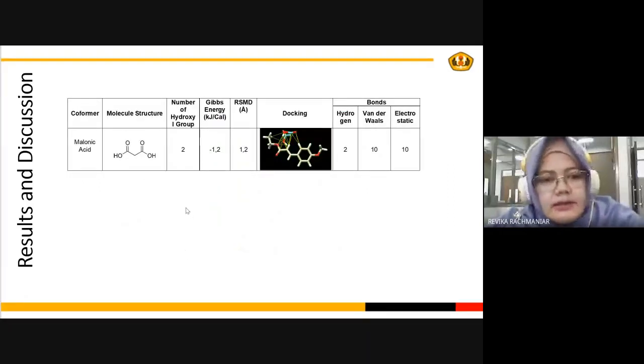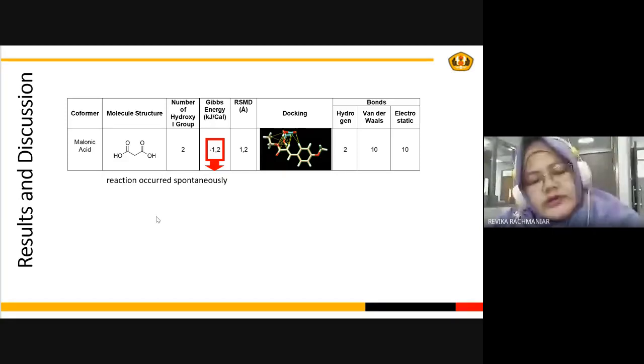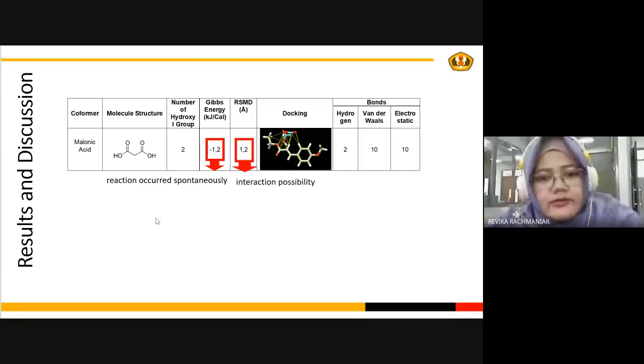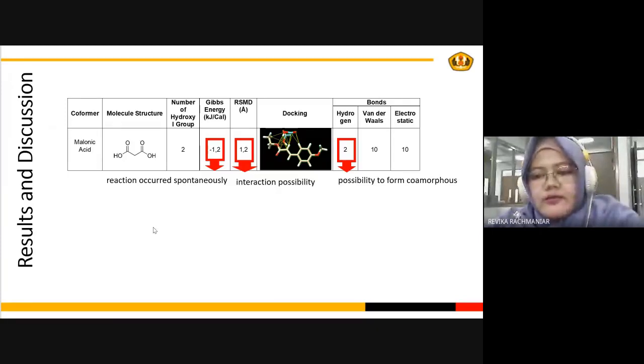And the last one is malonic acid. Malonic acid has two hydroxyl groups, and the Gibbs energy between malonic acid and APMC is below 0 kilojoule per calorie, so it means the reaction occurs spontaneously. The RSMD value is below 2, so the interaction is possible. And for the bonding between malonic acid and APMC, there are 2 hydrogen bonds, so it has the possibility to form a coamorph.